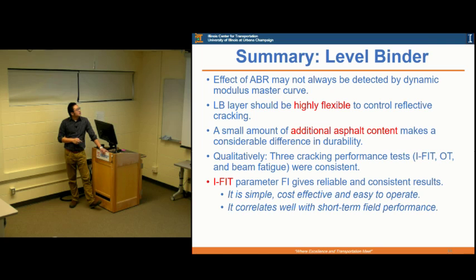This is for the level binder part, as I mentioned. We can see some findings, but I don't consider this a conclusion yet because the project hasn't been completed, but we can see some findings here. Basically, the ABR cannot always be detected by E-star, since E-star is just focused on the non-destructive range, so you don't go into that destructive range. Also, the level binder should be highly flexible to control cracking.